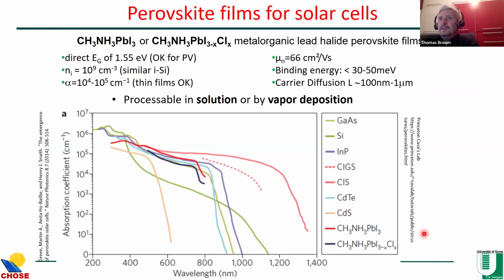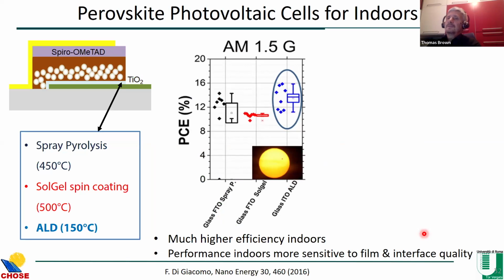So why methylammonium lead iodide perovskites? They have high absorption coefficients, so only a few hundred nanometer thickness of the semiconductor is used. High diffusion lengths, which are of the order of the film thickness, and they can be processable in solution, so they can be printed. So the device structure is transparent substrate like glass or PET, ITO, transparent conductor, compact TiO2 layer or SnO2 layer, sometimes a mesoporous scaffold so that the perovskite can grow over it. The perovskite film in brown, a hole transport layer, and a top electrode, which could be gold or carbon, for